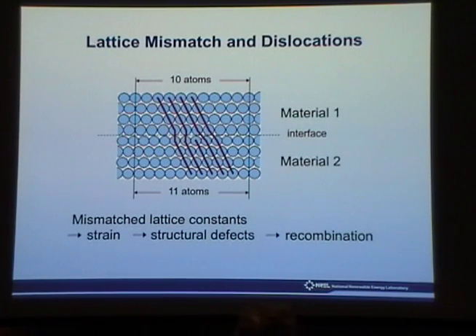Now, if the dislocations lie only in plane, then they're probably not going to be so problematic, but that's not what happens. They end up turning, and they go through your material. They're called threading dislocations, and that's when you really have problems. When your threading dislocations go through your solar cell material and really through the junction, you really create problems and lose voltage.